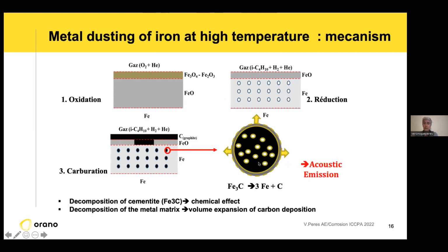And then we have some cementite formation, but it's not stable in this atmosphere. And we have production of carbon, which is coke and carbon nanotubes, and the decomposition. So we hope to have some acoustic emission from these systems.